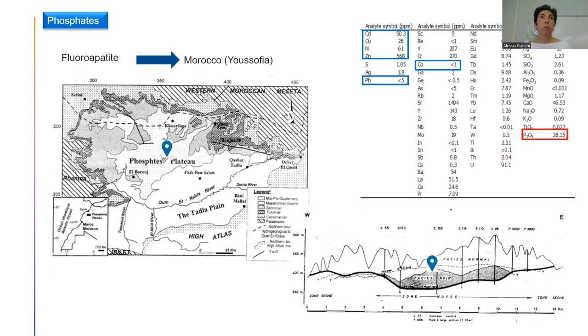Then we went to sample phosphate in Morocco. Morocco is the first country that produces phosphate, and we sampled along the phosphate plateau, asking permission of the company that is working in this area. And so we sampled two different types of phosphate, a black one and a white one. The black one, the color is due to the amount of organic matter, and obviously we characterized this type of fluorapatite. We didn't use the white one for this part of the study because it has a low concentration of phosphate, and you can observe the difference in phosphate concentration between the Moroccan phosphate and the US apatite is a really low value.